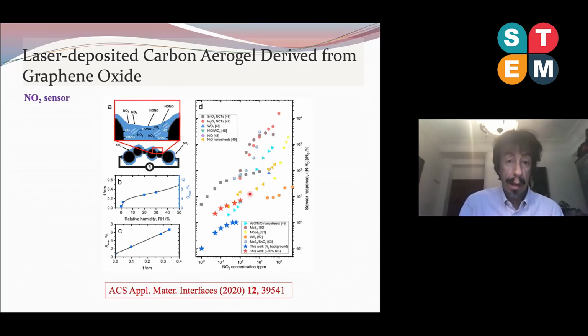And it's based on the enhanced solubility and reactivity of NO2 in a water layer which is surrounding this foam material, because these foam materials have hydrophilic functional groups like hydroxy and carboxyl groups. So there's always a very thin water layer surrounding them that favors the solution of NO2 and its reactivity. That's the reason why it works so well. And actually, the performance of this sensor is comparable and also competitive with other materials that are being used in sensor technologies.